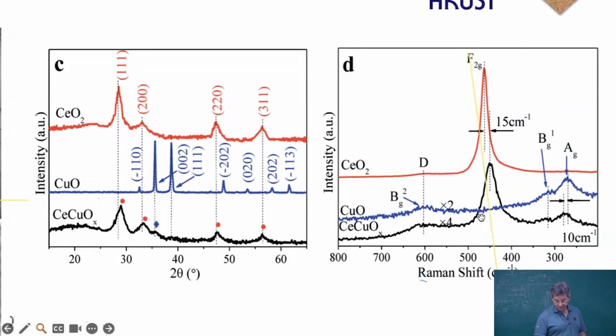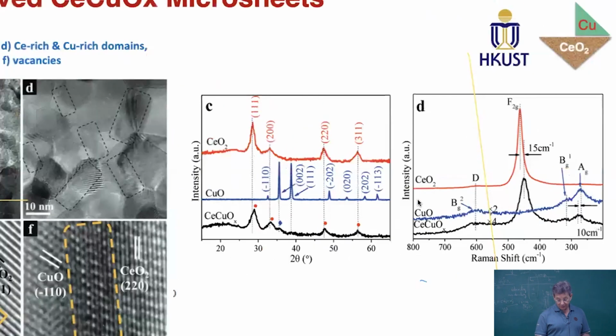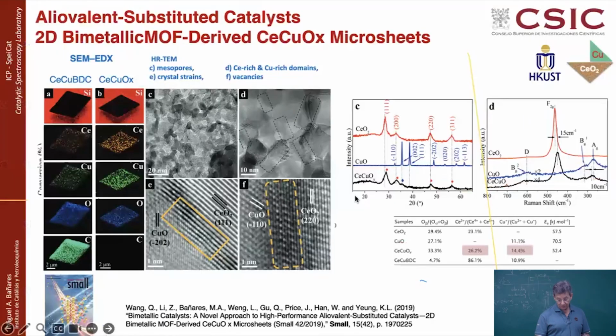Raman will report on these materials mainly about the ceria. This is the reference Raman band for pure ceria. This is for pure copper oxide, with these bands around 200 to 300, which are apparent here at essentially the same position. But the most interesting is that in the case of ceria, you get a significant distortion, a significant change on this major vibration of ceria. A 15 centimeters to the minus 1 shift in the Raman shift is quite a bit. So this is really telling you that you are getting a highly distorted, highly defected ceria, which is closely entangled with copper, and which accounts for an efficient activation of molecules.